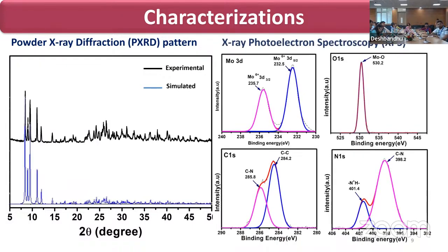We have also characterized it using X-ray photoelectron spectroscopy, from which we can confirm that molybdenum is in the +6 oxidation state. From the oxygen 1s spectra, we confirm the bonding between the metal and the oxygen. From the carbon 1s spectra, we confirm the bonding of carbon-carbon and carbon-nitrogen, and the nitrogen 1s spectra shows that the triethylamine nitrogens are in a protonated state.